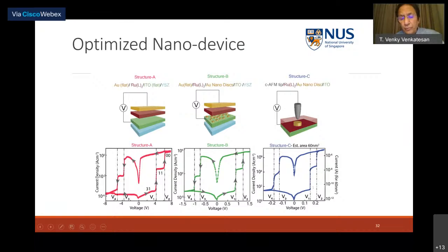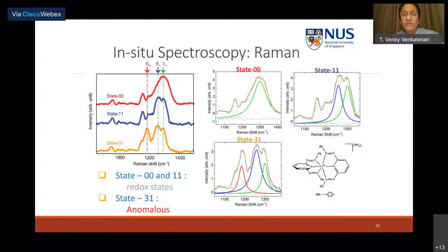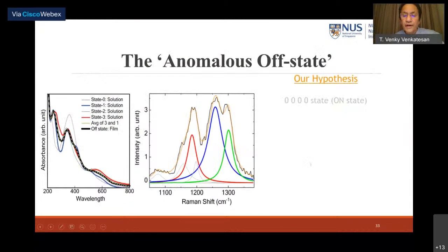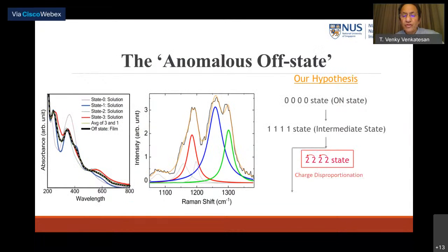Now, the bottom energy state arises from this. During the Raman spectrum, we arrive at what is called a mixed state, which is a charge disproportionate state. Instead of forming 0, 0, 0, 1, 1, 1, 2, 2, 2, this forms what is called a 3, 1, 3, 1 state, where there are essentially 4 molecules sitting next to each other. You can see one has 3 charges, the next one has 1 charge, 3 charge, 1 charge, forming a very large dipole in the system, creating a huge molecular polarization.